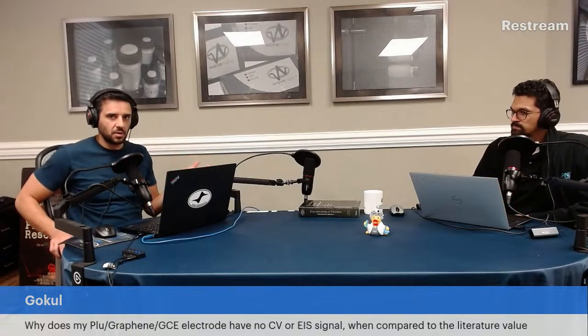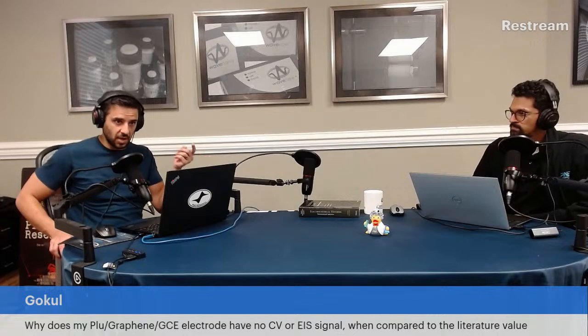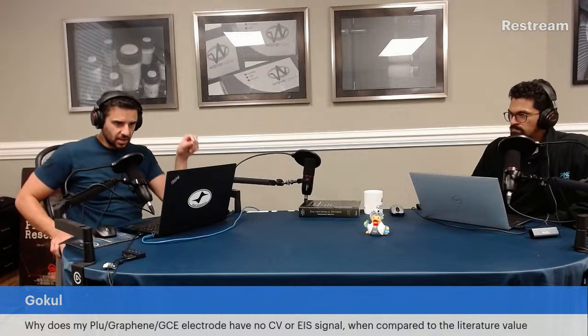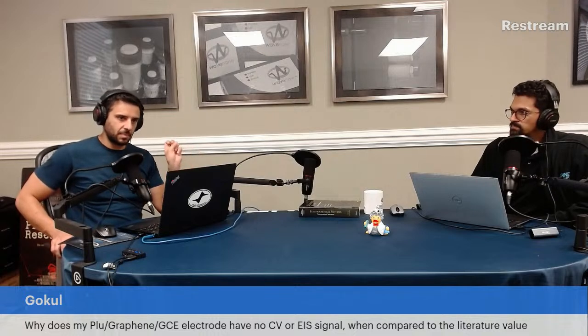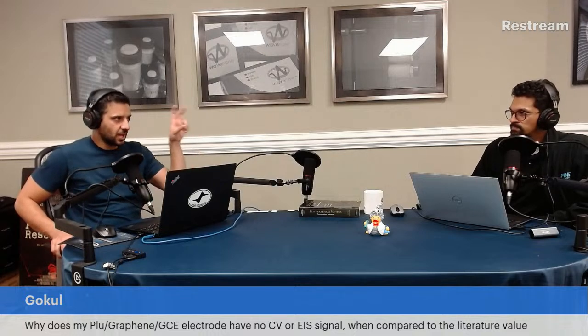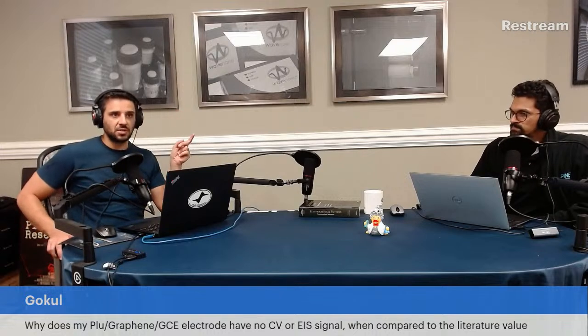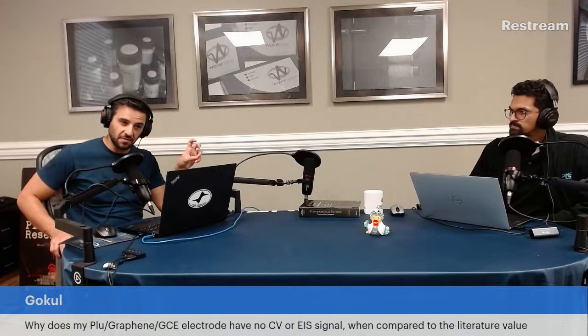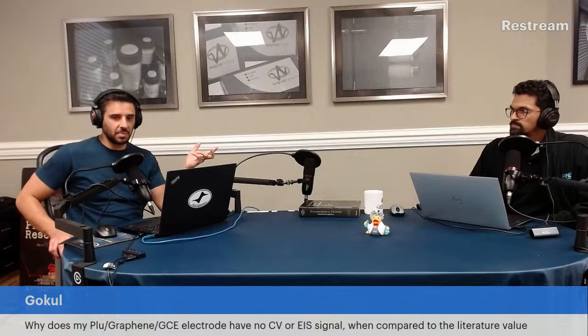If you have literature, research, and evidence that polyluminol is electrocatalytically active towards ferrocyanide, and people are showing that, one of two things is true. One is that very, very small response looked like there were some peaks, but they were really small. If you zoom in on the y-axis, you would resolve those. So one of two things is true. One is that it actually is catalyzing the ferrocyanide. You got to zoom in really far, and it's not nearly as electroactive as bare glassy carbon, which is bad. And so it appears somewhat insulating. It just has really low catalytic activity.